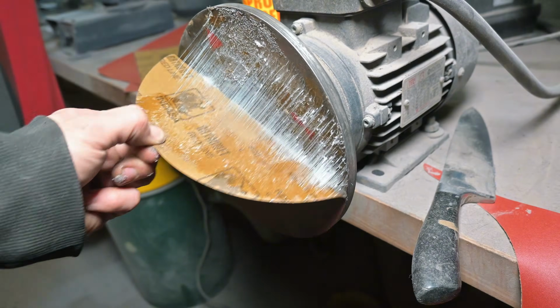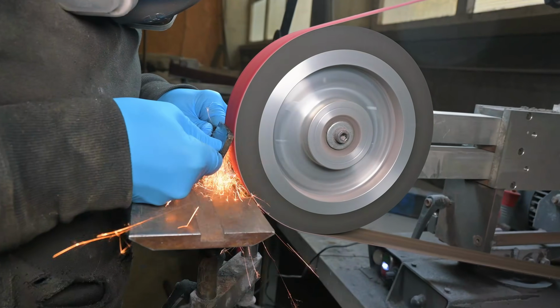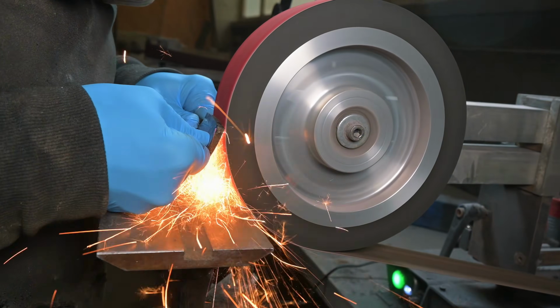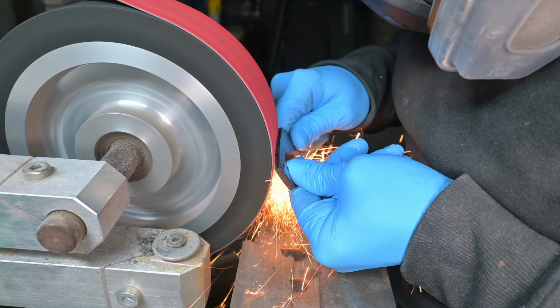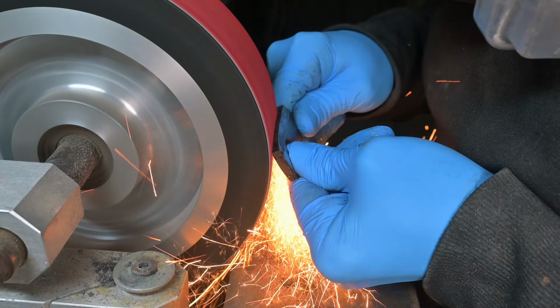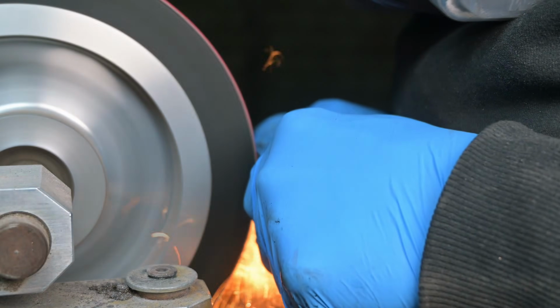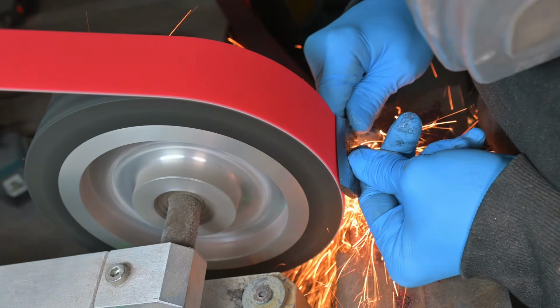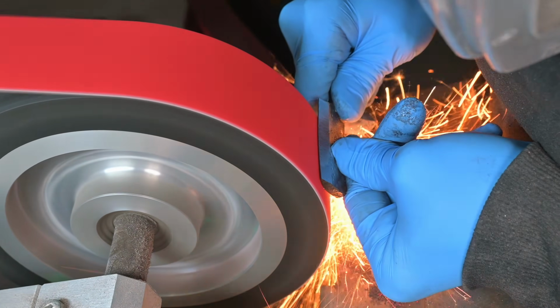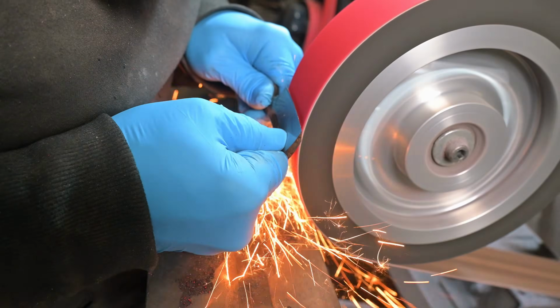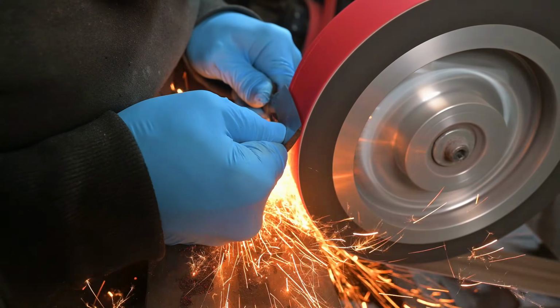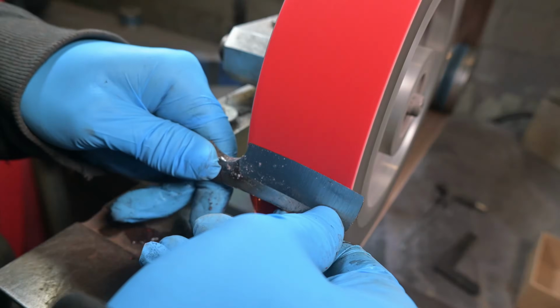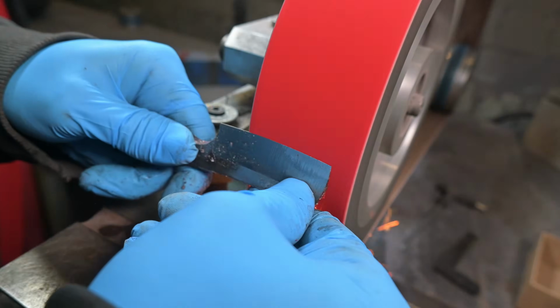I took my smallest contact wheel, which is an 8-inch contact wheel. With a razor, you want to have a really deep hollow grind and an edge that is so thin you want to grind it to a zero edge. If you are grinding a razor, be super careful with overheating. The edge is so thin and can burn in a millisecond. So always use fresh belts, take it slow and cool your knives.